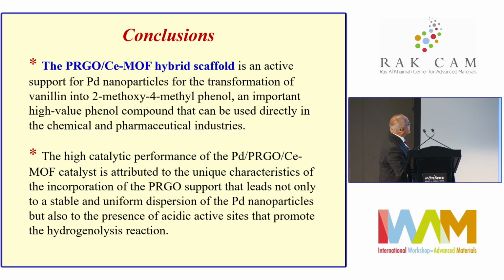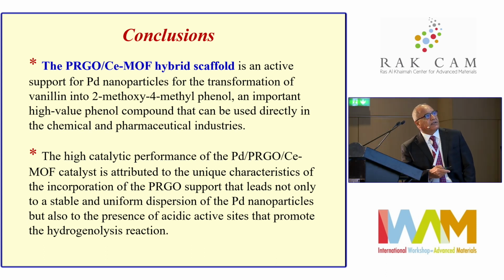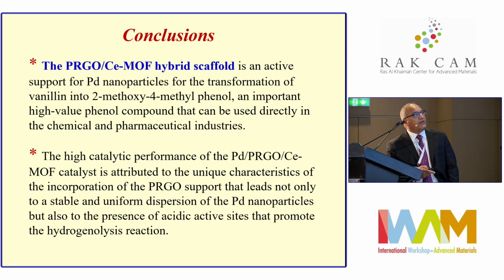So this is the first example. We can say that the partially reduced graphene oxide cerium MOF hybrid scaffold is an active support for palladium nanoparticles for transformation of vanillin into 2-methoxy-4-methyl phenol, which, as I mentioned, is an important value-added compound that can be used in the pharmaceutical industry and in many other chemical industries. We believe that the good activity of the hybrid support is due to the incorporation of reduced graphene oxide, which leads to good dispersion of the palladium nanoparticles, and also you still have graphene oxide in the hybrid structure, which has acidic properties, important for this reaction to accelerate the formation of the phenol. So that's the first example of the hybrid structure solving the problem of weak support from the cerium MOF by itself.